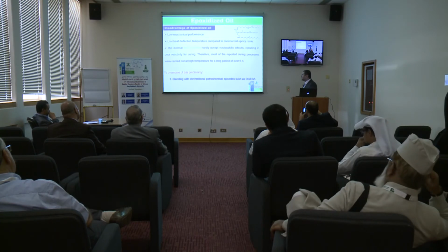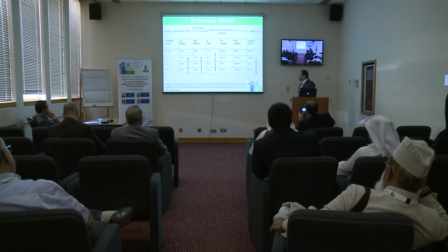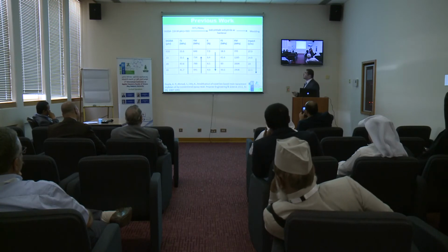To overcome this problem, they blend with conventional petrochemical epoxy, so they mix the commercial product and the epoxidized soybean oil. The other approach is the addition of filler. In previous work by Gupta et al., they blended diglycidyl ether of bisphenol A, from 10 to 30%, with epoxidized soybean oil, with addition of the hardener.